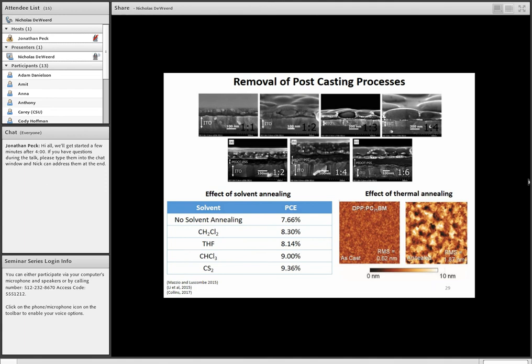you can control morphology a couple different ways in terms of the solvent that you're using to spin, or if you're on the industrial scale, print your device, or vapor deposition. You can control the rate at which it's deposited, and that'll change the morphology, or the fullerene acceptor donor ratio. So you can change a lot of these variables and control the morphology without having to do solvent annealing and thermal annealing, which is going on in the top set of images. And I've discussed this image before.